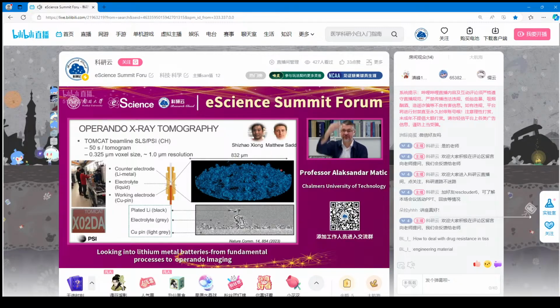So if you take a vertical cut through the cell, this is what we observed then, that we could see lithium structures formed. And in some places, you can see these very large dendritic type of structures formed when lithium is just growing, and you get enhanced growth at some protrusion.